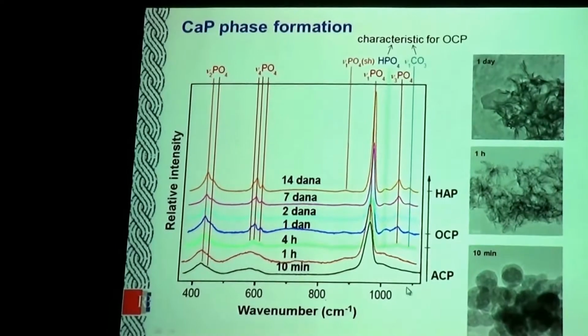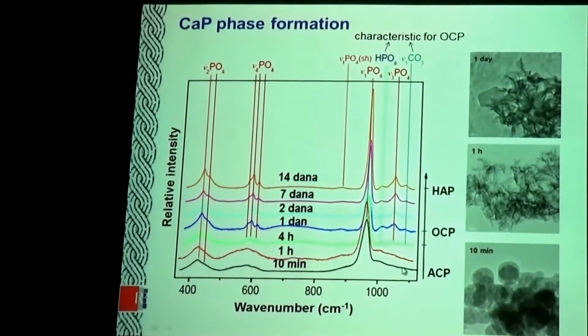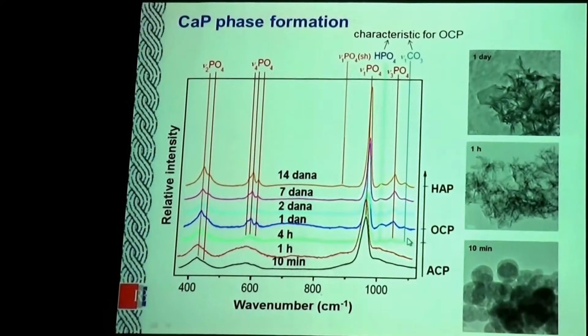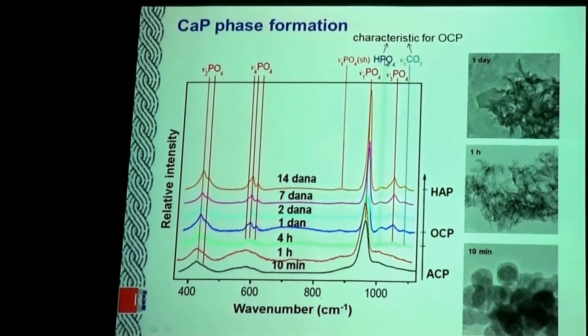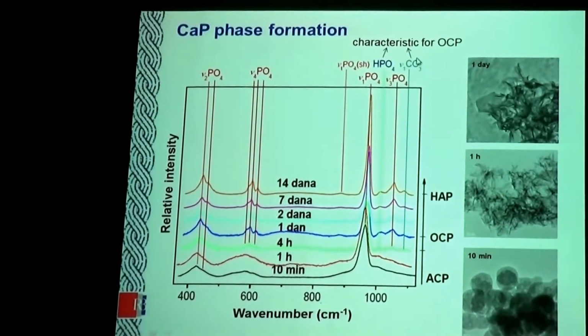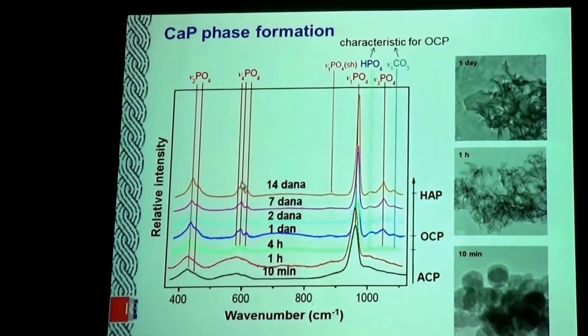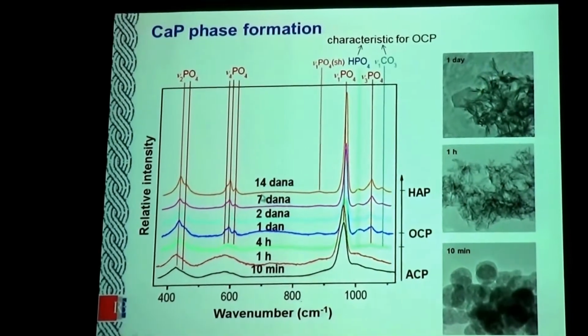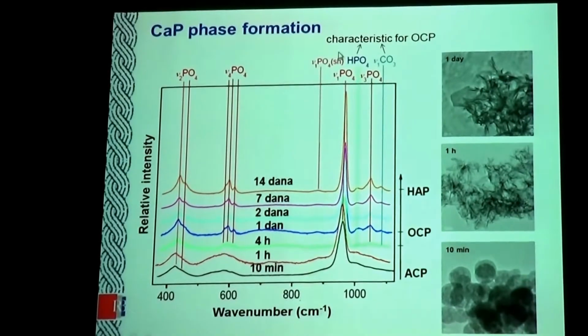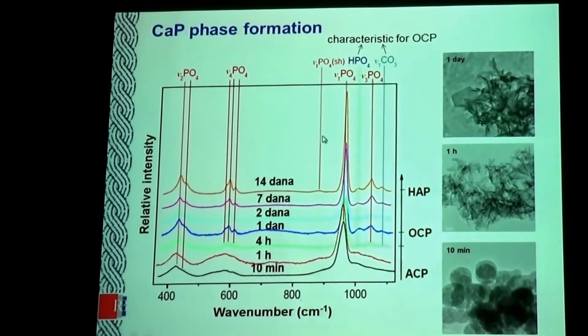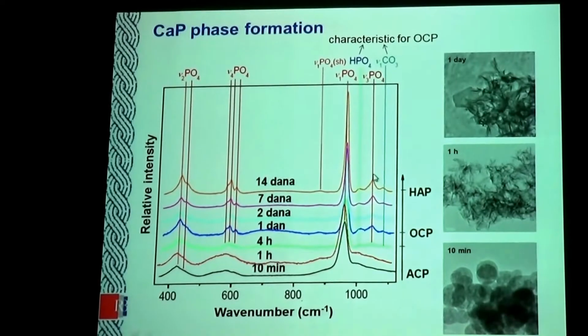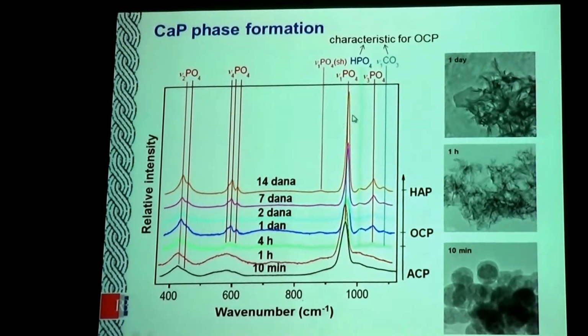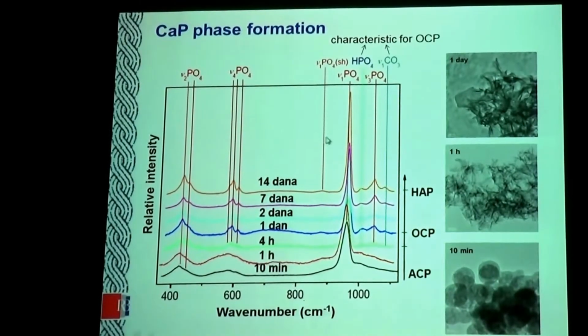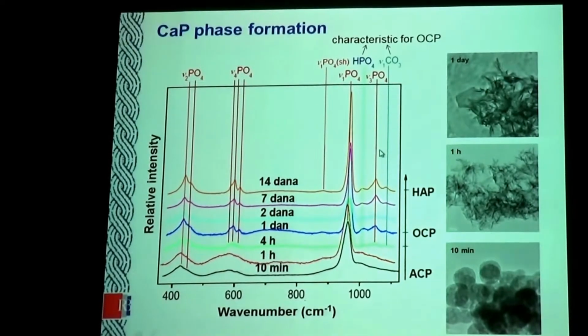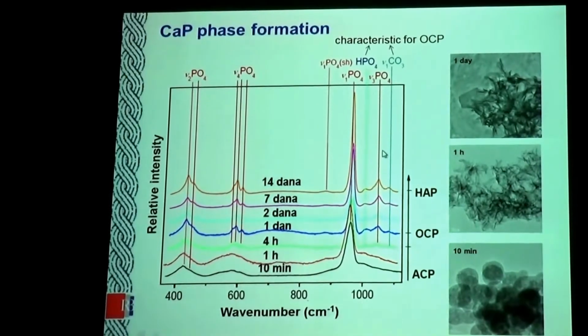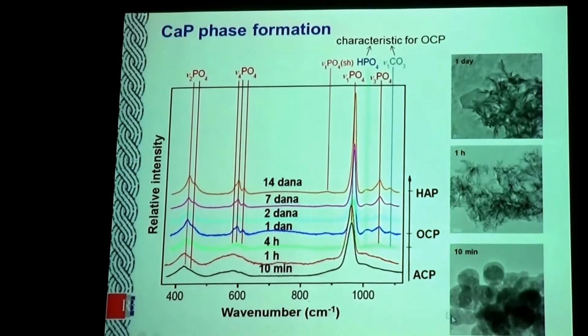You can easily observe that after 4 hours, bands characteristic for octacalcium phosphate appeared, and we needed 2 weeks for formation of hydroxyapatite, since in this case the bands are much narrower and the shift is much larger. So due to position of the bands and also the bandwidth, we can conclude which phase we had.